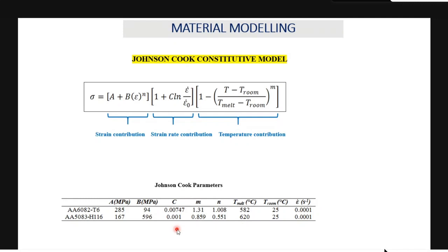There are some traditional constitutive models, and they show good agreement with the experimental conditions. So we can go for any of these cases based upon the data availability and the accuracy of the model with the experimental conditions. The first one is the Johnson-Cook constitutive model. This is a well-known model, very famous for simulating the large deformations happening in various processes like compression test, tensile test. You can go for any low strain test, high strain rate test. So you can go for all the tests with this model. Here the flow strength is a function of the strain component, strain rate component, and temperature component. So including all the parameters, we can get the exact behavior of the material.